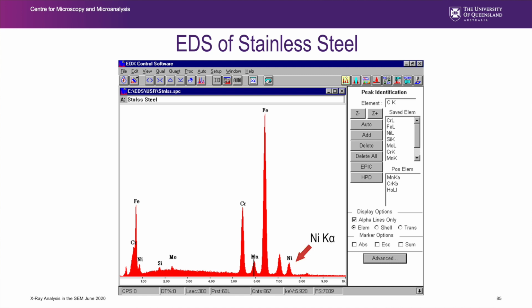This is the nickel K alpha, this is the nickel K beta. Here's an interesting fact. This is the chromium K alpha, and here is both the chromium K beta and manganese K alpha, if manganese exists. Do I label it? Do I put it into my analysis?